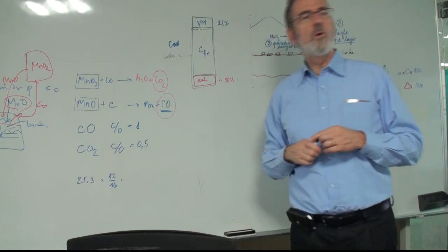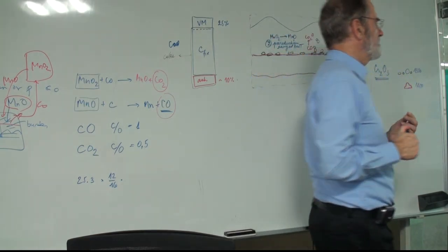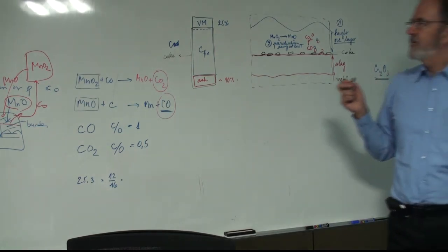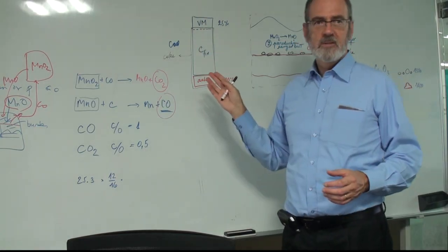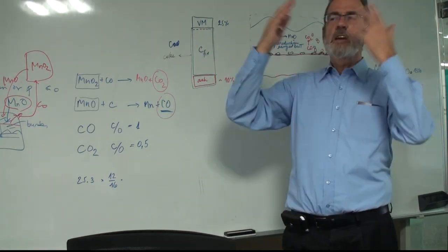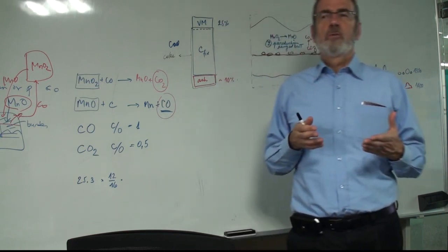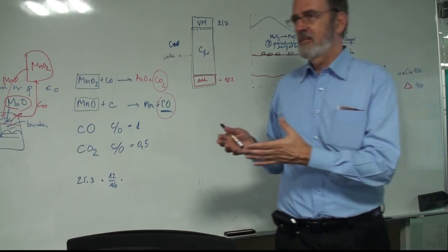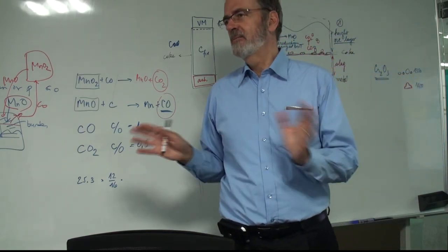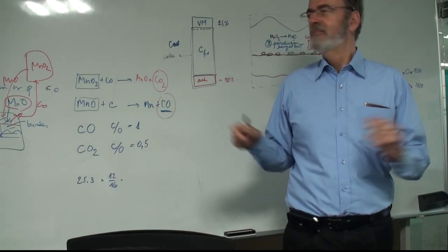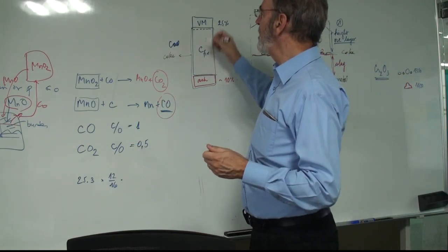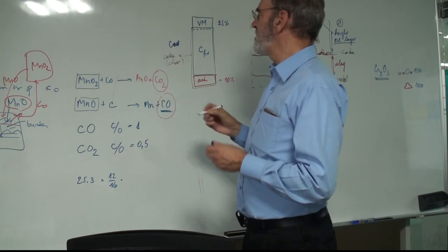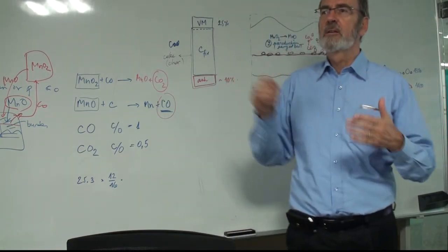And this is coke. If you do this pyrolysis, meaning heating up a coal which is not coking, the result is called not coke but char. So if you have no coking coal, it is called char. Coal char, or char.